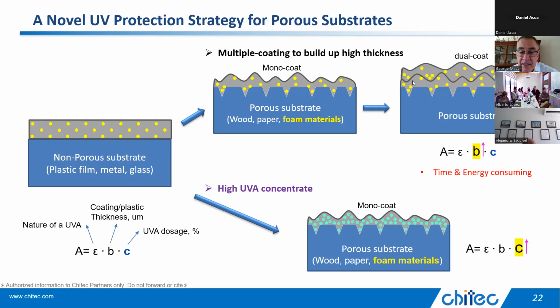So like on a deck coating or something like that, where you put on 3 layers, now you're putting on a lot of extra film and it's extra labor to really pile on that thick layer that absorbs all of the UV light. And what you can do now with the R455, you can concentrate it into your resin system at a higher level than you can do when you just add a free UV absorber.